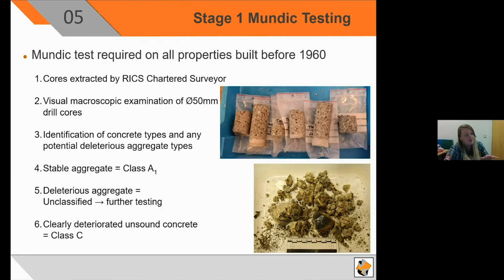We do a visual macroscopic examination of 50mm drill cores. We identify the concrete types, deleterious aggregate, and any stable aggregate found at this stage is given an A1 classification, and any deleterious aggregate remains unclassified and is recommended for further testing. The only exception is concrete that is clearly in unsound condition, which is referred to as Class C condition.